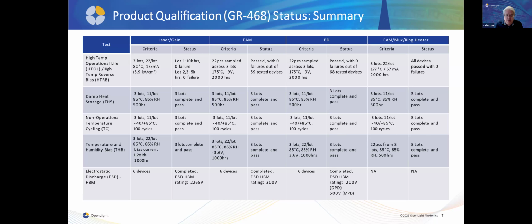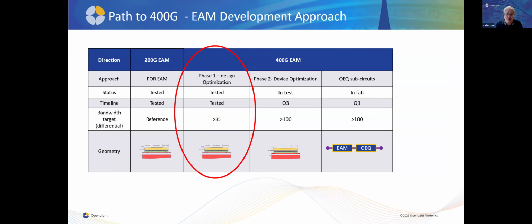So that's great. So now we need to move from 200 gig up to 400 gig, and there's a couple of ways you can do that. As I mentioned, we like electro-absorption modulators because they're physically small, and to double the bandwidth, you can start really by optimizing the device design. You can shrink the ridge width, you can shrink the physical length of the device. Changes to the RC time constant are really how you go from 35 to 85. And so what we've tested in the lab, and the results I've showed today, we're showing better than 85 gigahertz differential bandwidth with pretty much the same structure.